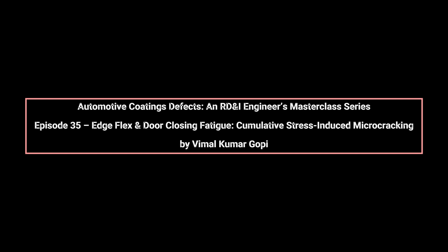Detection of edge fatigue failures requires close inspection and often magnification. Linear cracking parallel to door edges, paint lift at corners, and gloss loss confined to closure perimeters are characteristic signs. Accelerated durability testing combines mechanical cycling, thermal shock, and humidity exposure to reproduce these failures before production release.